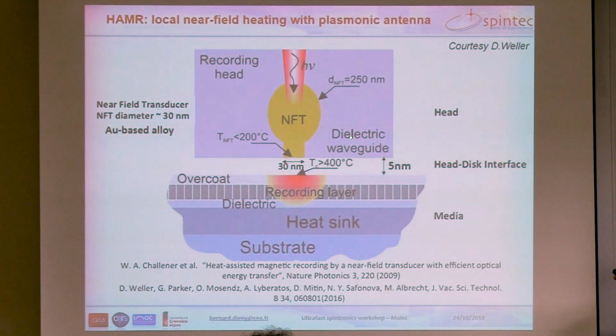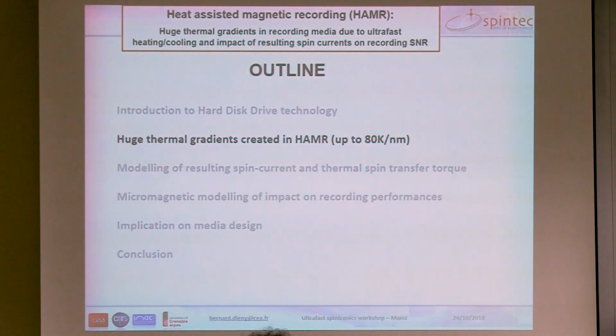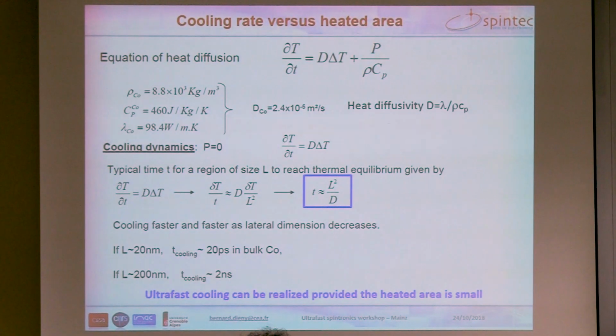It has a lollipop type of shape, and at the end here of this plasmonic antenna, the size is 30 nanometer. So it allows us to create a heated spot on the media of the order of 30 to 40 nanometer. So let me explain now that thanks to this local heating and the motion of the media, we can achieve very strong thermal gradients in the media.